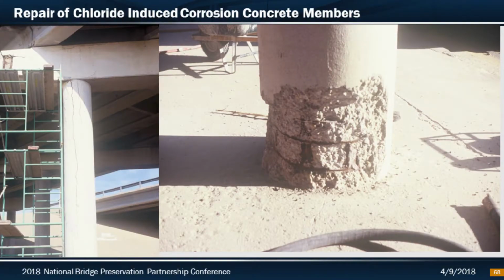This particular project was one of the early ones, so it did use a lot of glass fiber on several of the structures. It was 3 layers of glass fiber wrap and then 1 layer of CFRP. Apparently at the time it was about the same cost just due to labor. Carbon fiber was extremely much more expensive, but 3 wraps of glass was similar to 1 wrap of carbon. So I want you to keep in mind these are the before pictures of the extent of the damage. Again, this was widespread over many structures. Reinforcing steel was corroded. Delaminations were already coming off the columns all the way back down to the reinforcing steel.